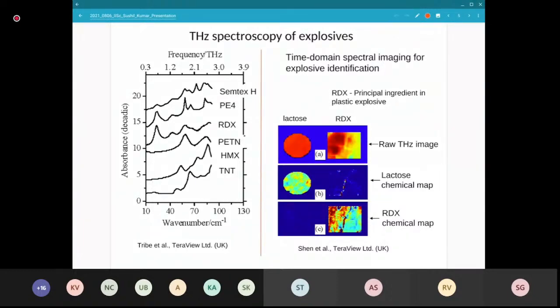So the challenge here is that terahertz is absorbed very heavily in water and any type of liquid. To give you an example, the absorption loss of water at these frequencies, around 2 to 3 terahertz, is about 600 per centimeter, which I evaluated comes to about 10 dB loss for a 40 micrometer thick channel of water. So you'll have about 90% absorption in just that thin layer of water. And methanol has maybe 2 to 3 times smaller loss, but it's still of the same order.